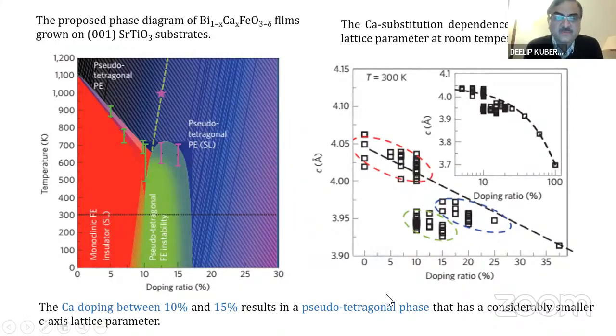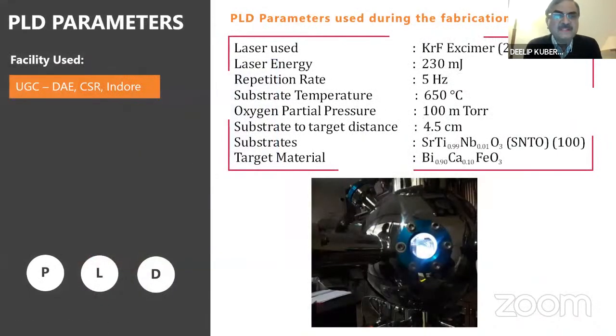and you can synthesize those materials. Therefore, I synthesized these BCFO films, these are calcium doped BiFeO3 films, using a PLD facility. Now in my department, I have established in the last 3 years a pulsed laser deposition facility, which is regularly used. But earlier I used to use the facility of UGC DAE CSR. This is the KrF excimer laser, and these are the laser parameters. And this is the substrate.